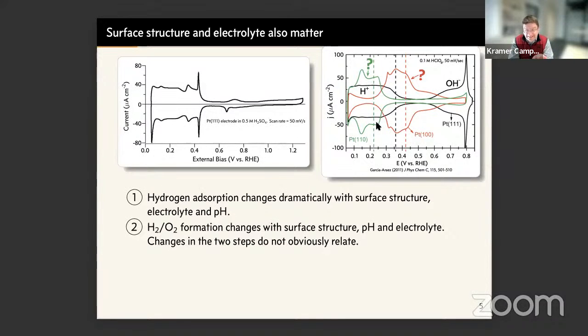What I want you to understand from all of this is that these voltammograms make clear that hydrogen adsorption on platinum changes dramatically with surface structure. It apparently changes dramatically with electrolyte. I did not show you any data, but it's well established experimentally that it also is strongly a function of pH. You can do similar experiments and look at the formation of hydrogen and oxygen, and what you find are similar conclusions: that this hydrogen and oxygen formation changes with surface structure, pH, and electrolyte as well. And of course, inconveniently, these two things, hydrogen adsorption and H2 formation, do not necessarily correlate.